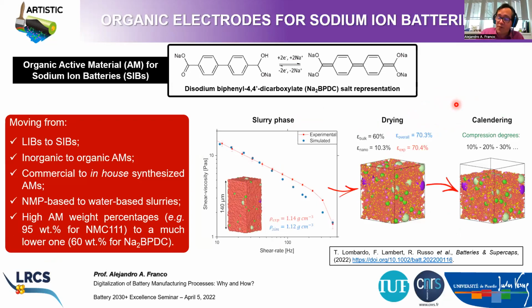This work, which consists of simulating slurries, drying, and calendering using the physics-based model, was extended for other types of materials, beyond NMC and beyond graphite. Those are the materials I was talking about at the very beginning of this seminar. So we extend this work for organic materials for sodium-ion batteries as a demonstrator that these artistic manufacturing models are chemistry neutral. They can apply to different types of chemistries, even chemistries that are far away from the ones that we currently use in commercial lithium-ion batteries, like NMC 111, graphite, and so on.